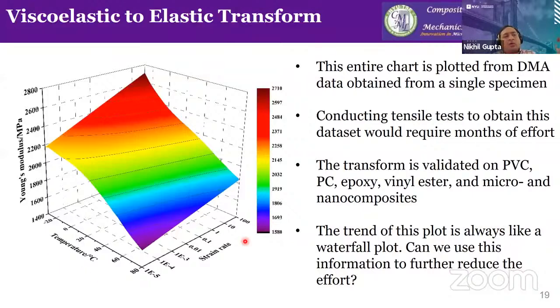So you can imagine that we had required 600 plus specimens to capture the same kind of data from tensile tests, but now we don't have to do those 650 tensile tests, but we get the data from one sample. It takes about 8 hours, and we get the same kind of data set from there. So this kind of transform was validated on PVC, polyvinyl chloride, polycarbonate, epoxy, vinyl ester, and many types of micro and nano composites, fiber reinforced composites. There are some special conditions for directional materials like fiber reinforced composites, but other materials like just the plastics, PVC, polycarbonate, epoxy, and vinyl ester, this was pretty straightforward.